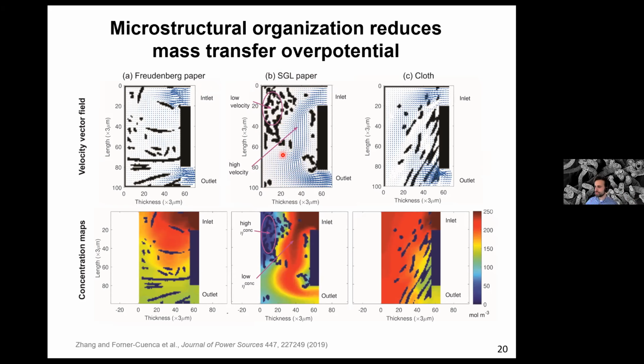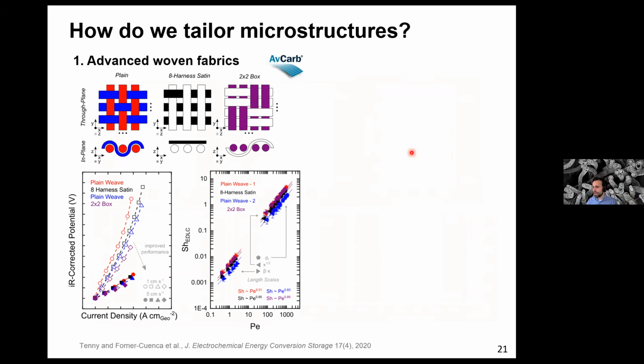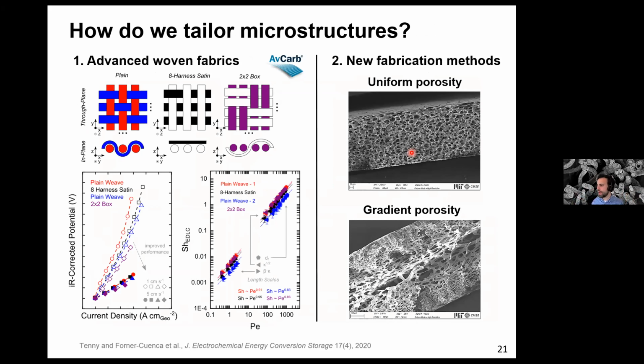And the reason we believe is that you have these big pathways here that give you high electrolyte flow velocity, and then these stagnant areas over here where there is essentially 100% conversion. So your electrochemical reactor is actually underutilized, right? You have big areas of the reactor that are not producing any current, and some small areas that are producing all the current. And that is a situation that is suboptimal from a mass transfer point of view. When you go to very aligned pores, hierarchical structures, then you get the best of both concepts.